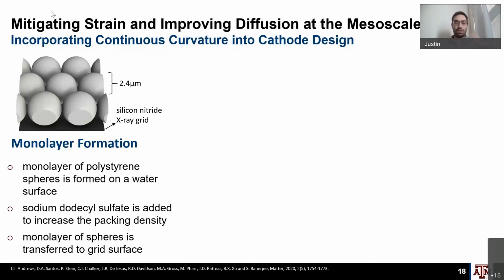One material we've been interested in for a while is inverse opal structures. To give you an idea of what these are, we take a substrate, typically a silicon wafer, but in some of the work I'll be showing you, we did this on silicon nitride STXM grids. We make a monolayer of close-packed polystyrene beads.